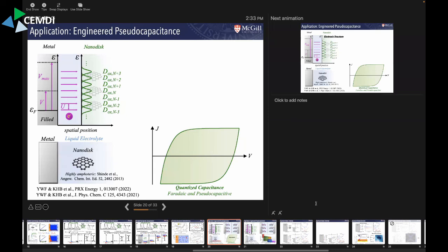But what we're arguing is there's this limit where, for storing the same number of electrons per unit area, say one electron for every 6 atoms, if you shrink the size of the disk, it pushes up the voltage that you want to store them, because now they start to Coulomb interact through the U. If you don't make the disk too small, they don't push on each other too much, so the so-called redox peaks or Coulomb peaks overlap in a very smooth way to give you sort of a metallic response, but through a Faradaic mechanism.